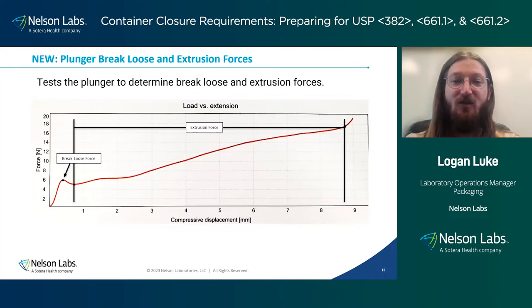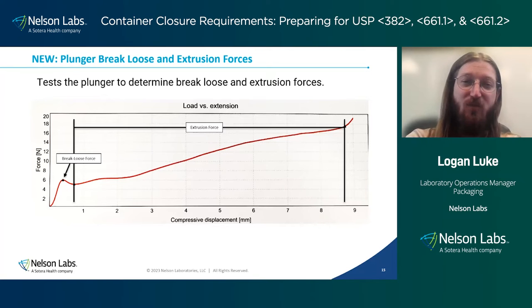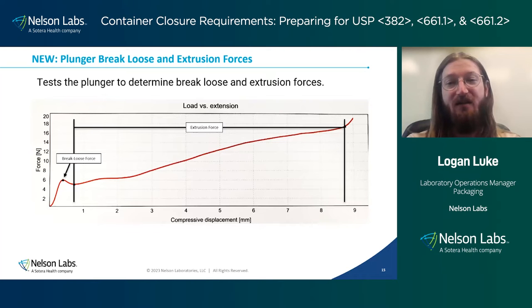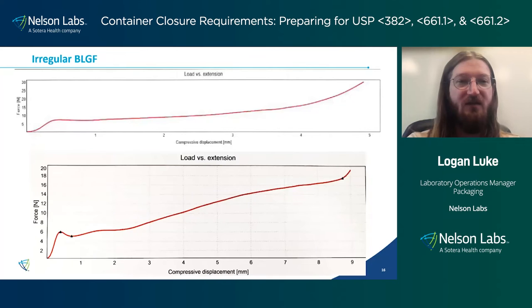If you're looking at these graphs, you should be on the lookout for things that are highly irregular. In this case, it's a pretty smooth slope all the way until the contents are expelled. But if you do notice something irregular, then you might see that it's due to non-homogeneous lubrication and might be worth investigating. Because there's a lot that can impact these break loose and extrusion forces, the acceptance criteria is left for you once again to define, and usability needs to be the main consideration when you're looking at your break loose and extrusion forces.